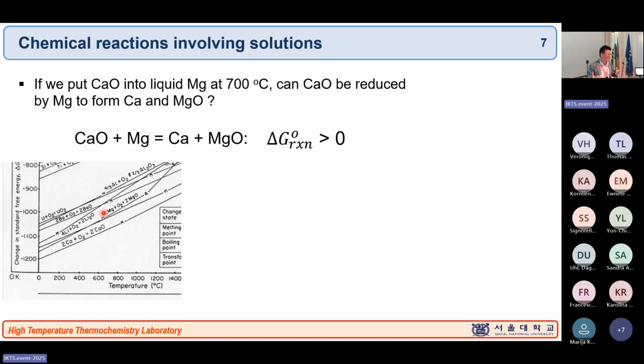This is the reality about thermodynamics. Theoretically, if you assume everything here is pure standard state, meaning it is not making any solution phase, this reaction cannot go forward. It's always in the backward reaction. So CaO is more stable than MgO. But in reality, if the calcium and the magnesium start to make a liquid solution at high temperature, about 700 degrees, both can make a liquid solution, then the dynamics can change.